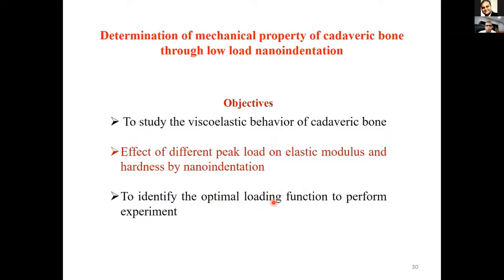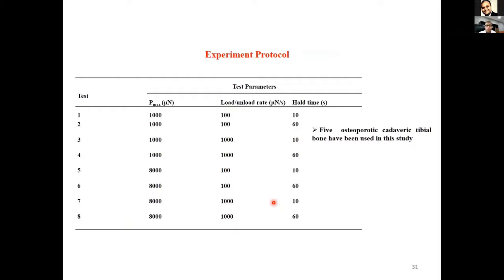And then some of the material properties, like the viscoelastic behavior of cadaveric bone, and how different peak load, elastic modulus and hold time are contributing to the viscoelastic behavior. We have taken five osteoporotic cadaveric tibia bones and applied some protocols. In the first case, we took a maximum load of 1000 micronewton, an unloading rate of 100 micronewton per second, and a hold time of 10 seconds, and we varied these parameters for different conditions for these five osteoporotic bones.